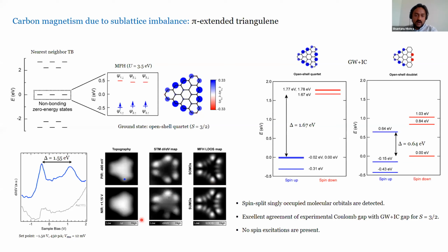To prove that the ground state could indeed be the quartet and not maybe doublet, what we did was some GW calculations, including the effect of the underlying surface. These two graphs show you the energy spectrum of this nanographene for the open shell quartet state and the open shell doublet state. The zero of the energy is fixed to the energy of the highest energy singly occupied orbital. And you see that the gap matches perfectly well.